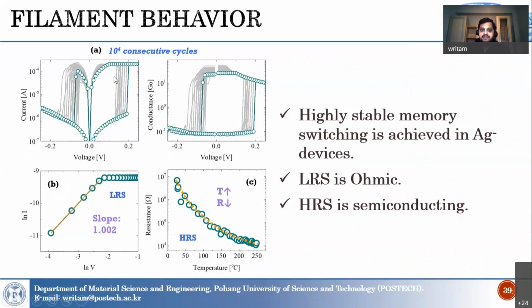And the device itself is very stable for the memory switching behavior. You can see this is the consecutive DC switching cycles for 10,000, and it was very stable. But the LRS was ohmic, pure ohmic, which was quite expected because of the silver migration. But the HRS, it was like semiconducting behavior.